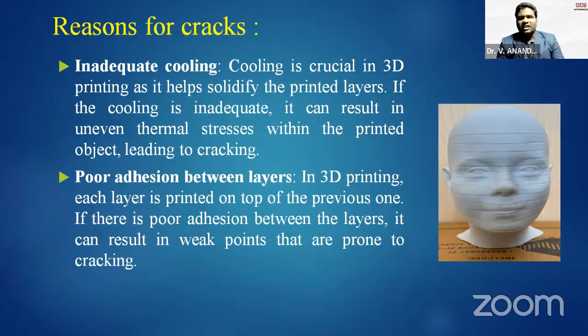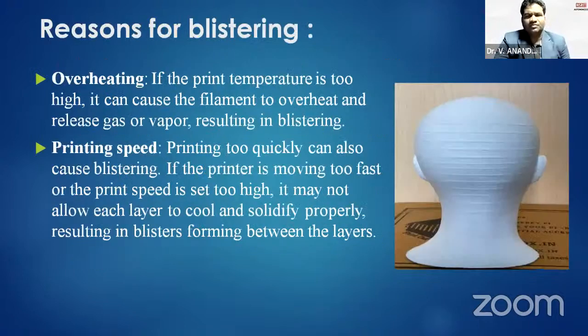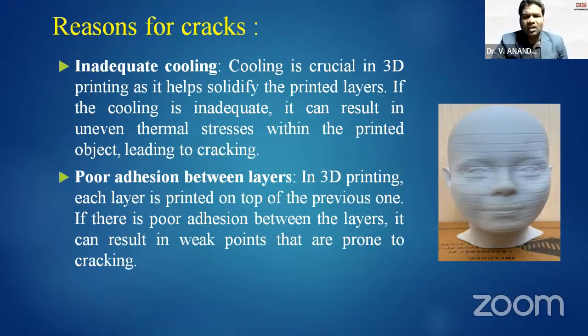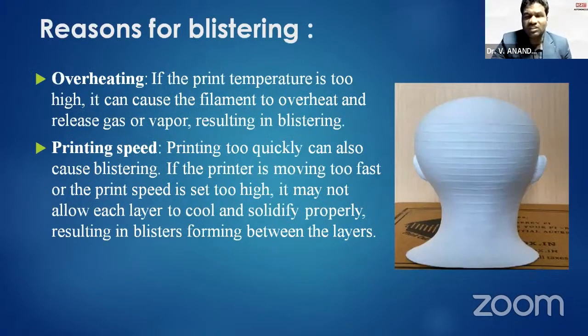Inadequate cooling of the filament which comes from the nozzle may be the cause of this type of defect. Poor adhesion between the layers is also one of the reasons for the development of adverse effects like cracks. Overheating is also one of the reasons. And if we have not set the correct printing speed, this type of defect may occur. So they observed that inadequate cooling, poor adhesion between layers, overheating of the filament, and the printing speed of the nozzle may be reasons.